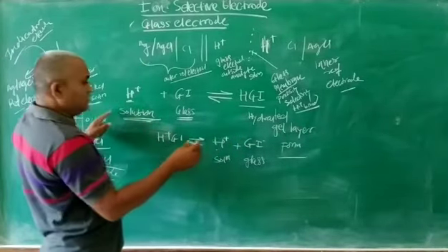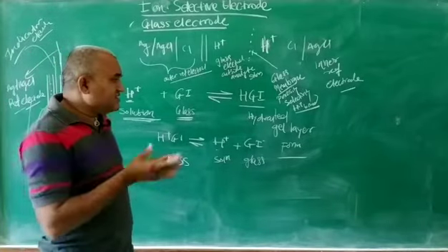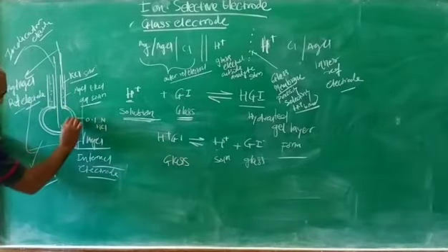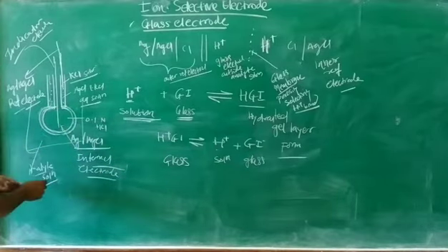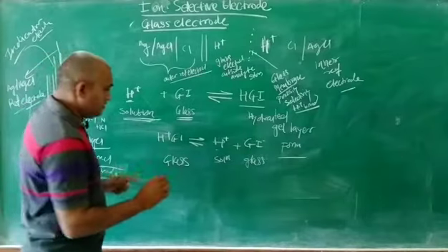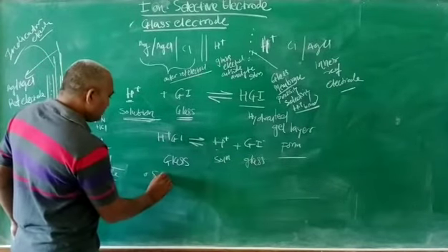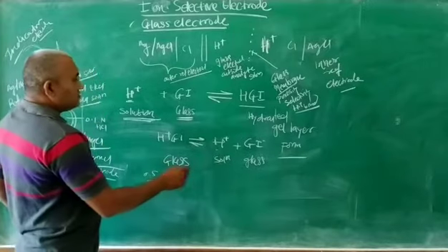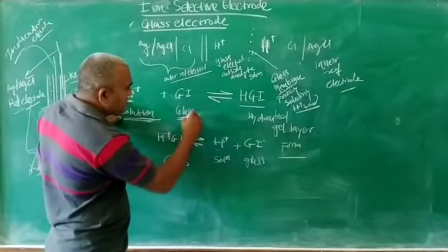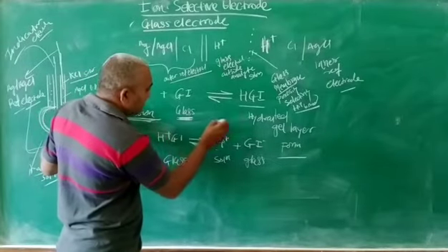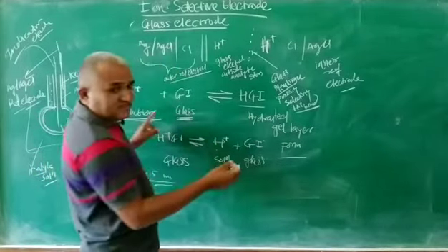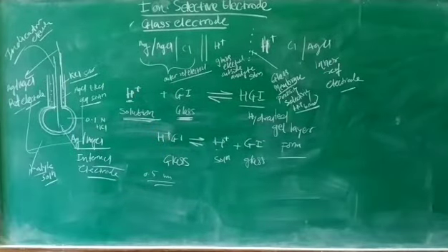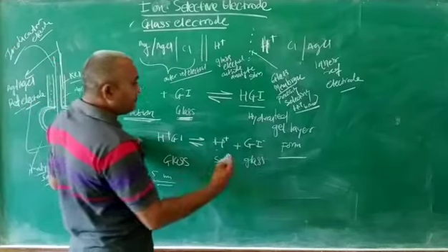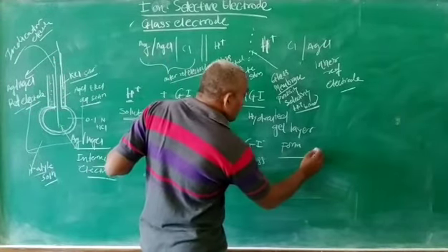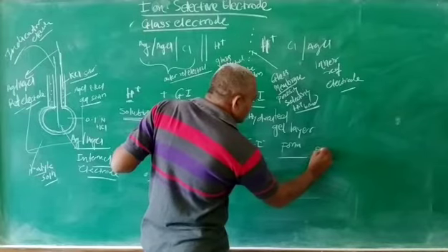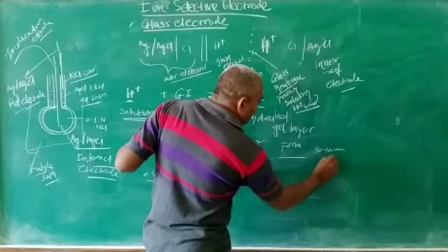So in the bulb there is a formation of a hydrated gel layer. The original thickness of the bulb is only 0.5 mm. So when positive ions combine with the composition of the glass, a hydrated gel layer forms. This gel layer forms with a thickness of 50 to 100 nm.